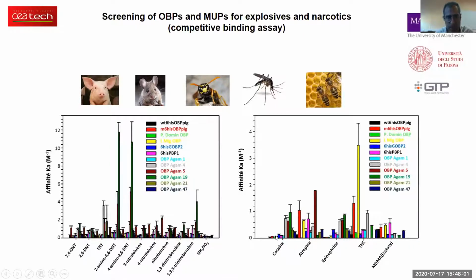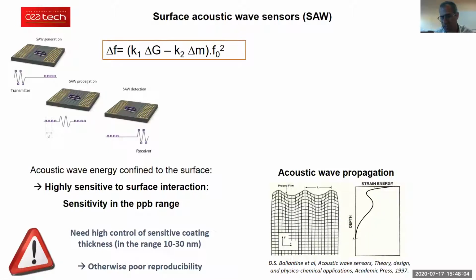They did this great work, and meanwhile we developed some diamond-based transducers onto which to immobilize these proteins. We were interested here in surface acoustic wave sensors. The principle is a piece of piezoelectric material onto which we deposit IDT electrodes. As we apply a potential to these electrodes, we generate an acoustic wave that propagates across the surface of the device, and this device can be brought to resonance. If we deposit a sensitive coating between these two electrodes, and that coating interacts with an analyte, this disturbs the propagation of the acoustic wave, and this is our measuring signal.